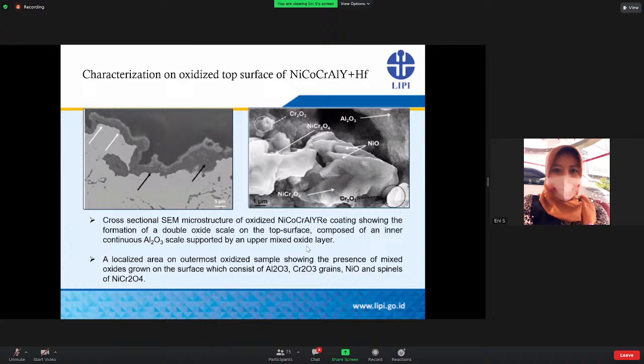of the oxide scales. A cross-sectional SEM microstructure of the oxidized samples shows the formation of a double oxide scale on the top surface, composed of an inner continuous alumina layer supported by an upper mixed oxide layer. A localized area of an oxidized coating is shown in these figures. According to the EDS point analysis, the outermost oxide layer consists of alumina grains, nickel, and so on, as described above.